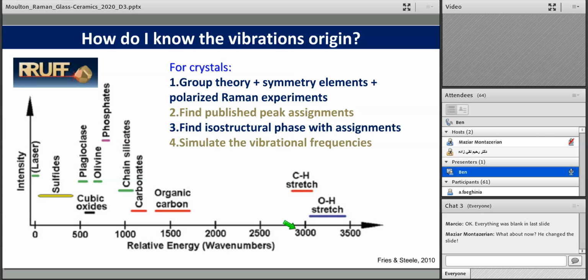But generally speaking, after you get a bit of experience, you'll see that the most intense features are quite distinctive for the different groups. This figure from Fries and Steele shows that chain silicates typically have bands here around 1,000. Carbonates are a little bit higher, organic carbons even higher. CH stretches and water bands are at even further removed wave numbers, up to 3,000. So it's not that bad, actually, once you get a hang of, or get familiar with, the different phases, determining what you're actually seeing. But how do you do it? You can do it the hard way, as I mentioned, with group theory, looking at all the symmetry elements, and you can do some specific Raman experiments called polarized Raman, and determine which symmetries correspond to which bands and make an assignment.